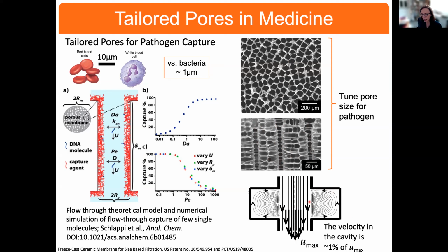And because of these side arms, if we have control of the size well enough, small bacteria compared to the larger red and white blood cells would flow through, and the smaller bacteria would be caught up in these side cavities. So we show that here schematically. And the flow in these side channels now is significantly slower than one sees through the main channel.